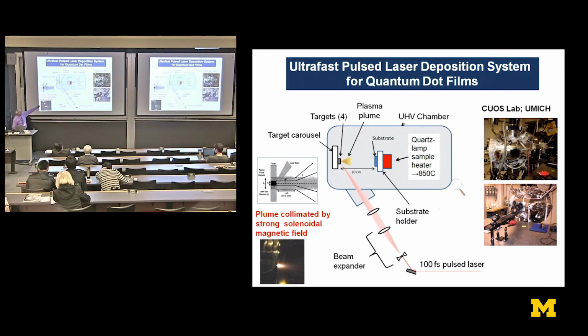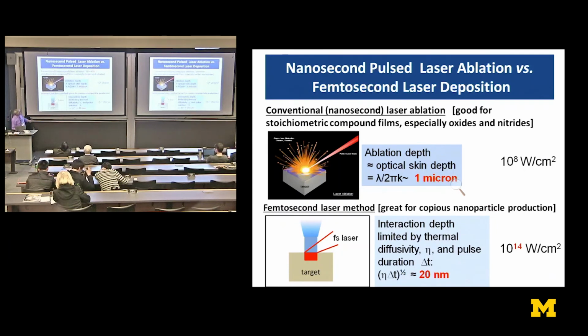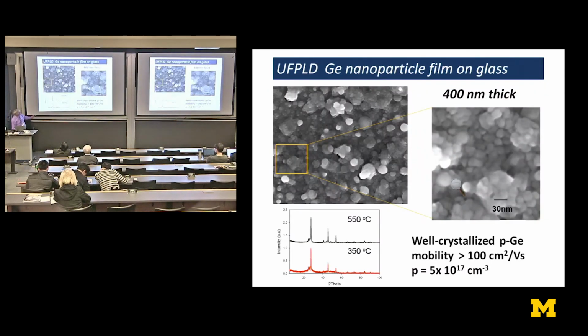with a target of germanium illuminated with a high power laser producing a plume which deposits a film on the substrate. I'll just show you the bottom line of the measurement. We do get copious amounts of germanium nanoparticles. They're well crystallized. They have a mobility of more than 100 centimeters squared per volt second. Those are highly interesting for PV applications. They're not as big as the bulk germanium mobility, but they're way bigger than amorphous materials and polymers and so on.